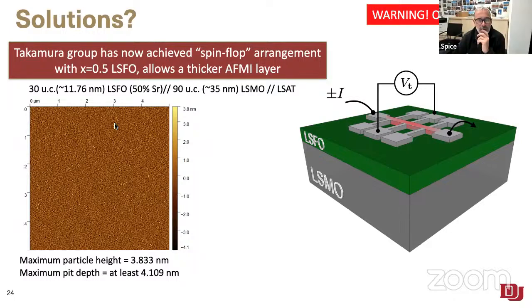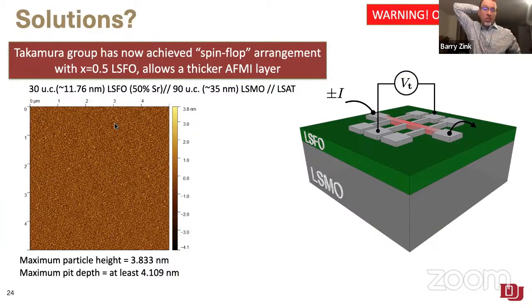This slide. Okay. So the point is just that Yayoi has been able to re-engineer things a little bit so that she gets the same coupling with a somewhat thicker antiferromagnet, which is nice because we can get rid of those missing grains and at least not have a direct connection between whatever we put on top of this thing and the LSMO underneath. Unfortunately, we still are having trouble where we have conduction and we think we're seeing charge effects in these materials. And I think that's just because, depending on who you're talking to, we may not always agree on what's an insulator, right?